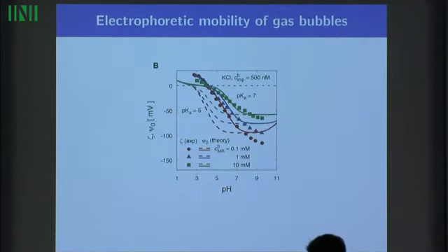And then finally, going back to where I started, this electrophoretic mobility of the particles. This is the zeta potential, a recalculation of the electrophoretic mobility using a Debye-Hückel-type model. You can recalculate that in terms of a potential at the interface. Negative potentials mean that the particles move in the direction of the positive electrode. That's what we see for air bubbles, as a function of pH.